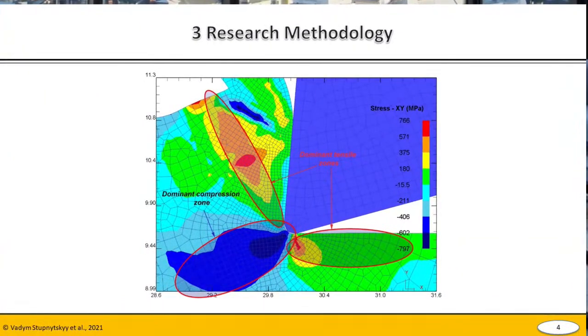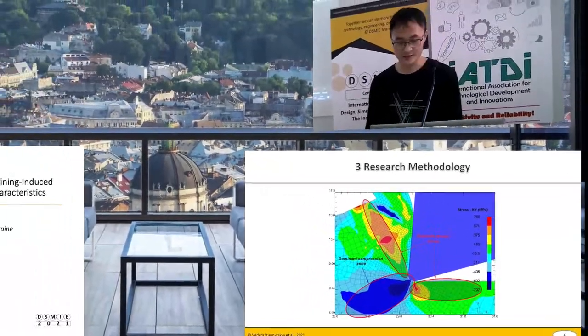When the tool is cutting into the material being processed, the wave of plastic deformation propagating in front of the cutting edge of the tool covers not only the chips, but also the material located along the cut line. Therefore, machined material at the cutting edge itself is subjected to the normal force and the friction force acting in the direction of the shear line. The normal force causes compressive stress, and the friction force induces tensile stresses of the surface layer adjacent to the front face of the tool. Thus the surface layer of the part is subject to inhomogeneous plastic strain, monotonically damping along with the cutting depth. Next slide, please.